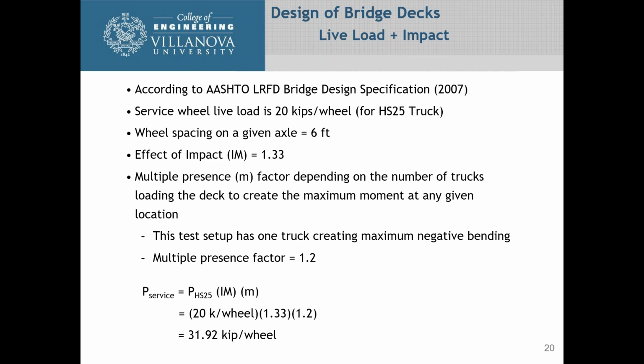The service wheel load is 20 kips per wheel, and this is for an HS25 truck. The reason we used HS25 is that in the Northeast, predominantly, most of the bridges are designed for HS25 loading and not HS20. The other parameter is the wheel spacing at 6 feet, and then the effective impact, which is 1.33.